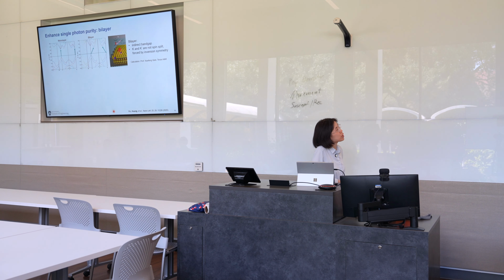So instead of using monolayer, we can look at bilayer tungsten diselenide. Because bilayer tungsten diselenide no longer has a direct band gap. So bilayer actually has an indirect band gap. And also because of the inversion symmetry for bilayer, the K and K prime values are no longer spin split.